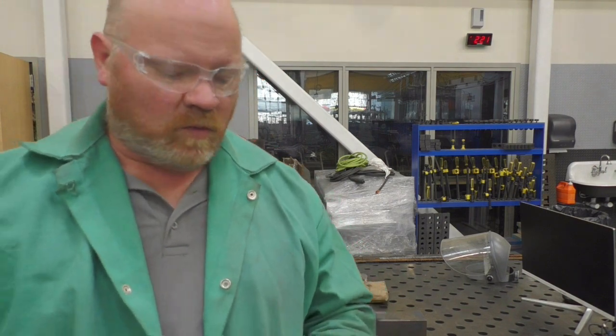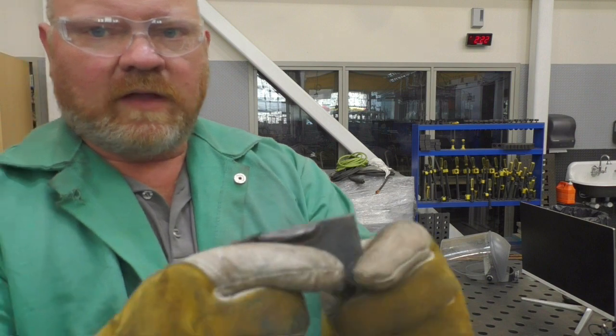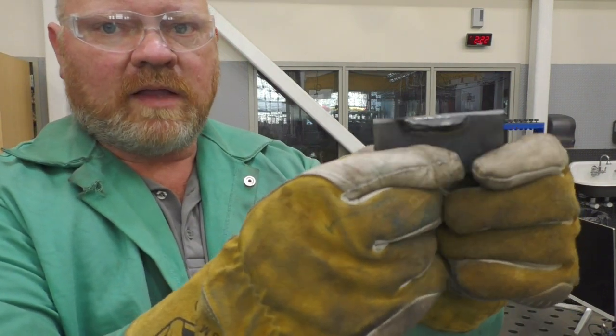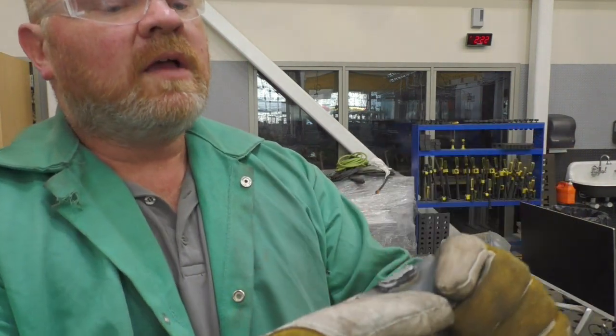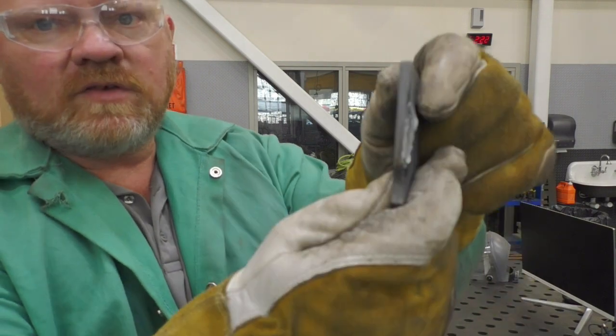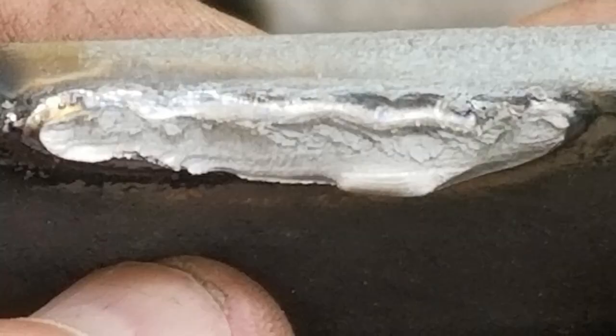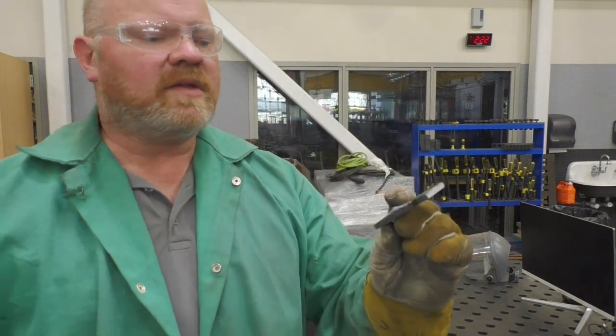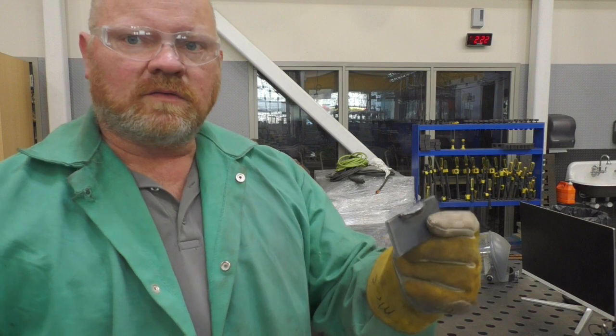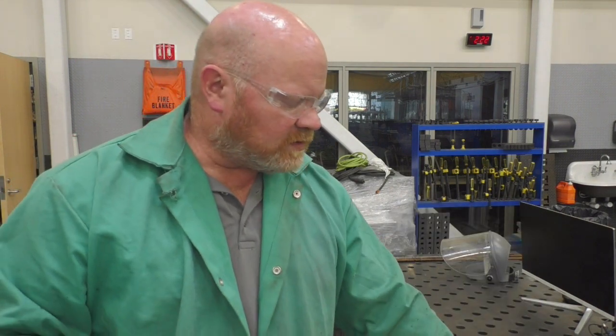It didn't break because the weld is weak. It broke because the weld is small. But again, if I look at my weld here, I can see a clean break, and I can look at the edge, and I can see that I clearly melted into the edge. I got good penetration. Now that doesn't tell me anything about my restarts, but it does tell me that the surface, which was covered in mill scale and maybe some light oil, did not yield porosity, pinholes.